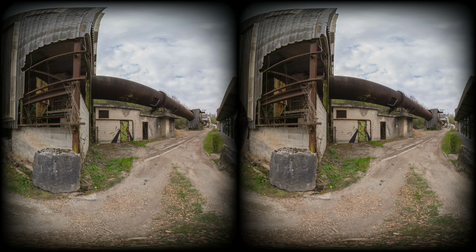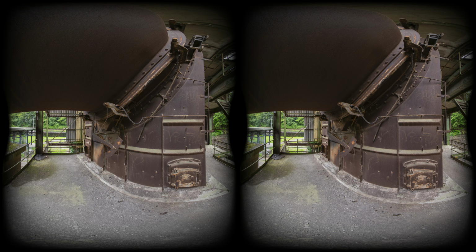The rotary kiln is an approximately 80-meter long, slightly inclined steel tube that slowly rotates at about 1 to 4 revolutions per minute. Through this rotation, the limestone gradually moved from the so-called cold end at around 200 degrees Celsius toward the gas burner. The furnace end heated to approximately 1100 degrees Celsius, where it was transformed into quicklime.